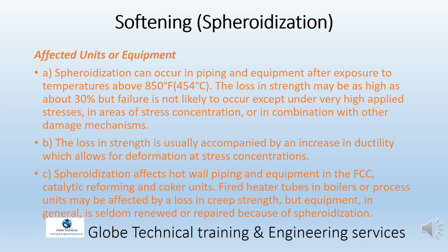Affected units or equipment. A. Spheroidization can occur in piping and equipment after exposure to temperatures above 850 degrees F, 454 degrees Celsius. The loss in strength may be as high as about 30%, but failure is not likely to occur except under very high applied stresses, in areas of stress concentration, or in combination with other damage mechanisms.